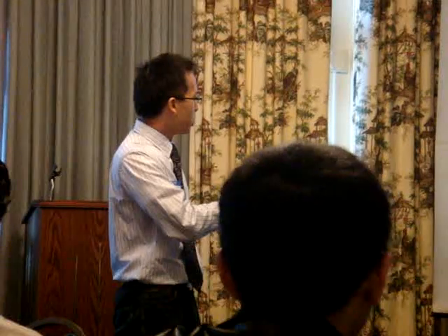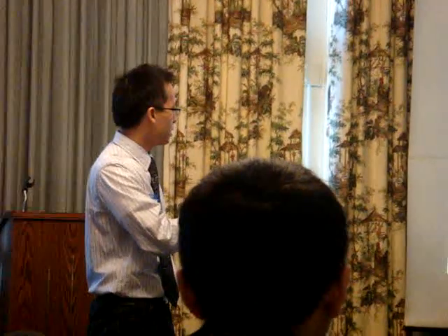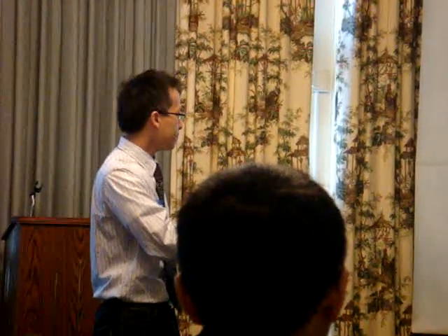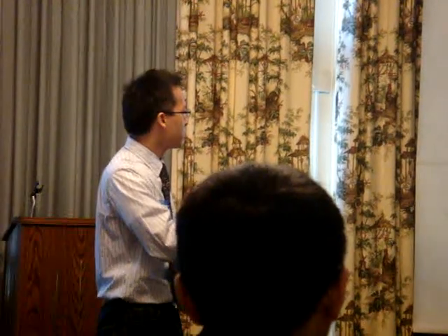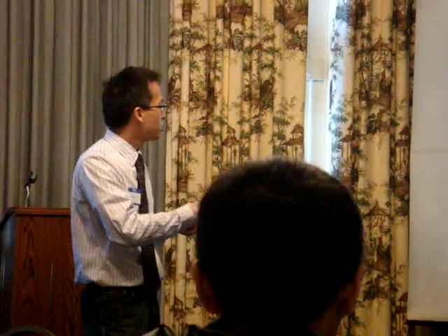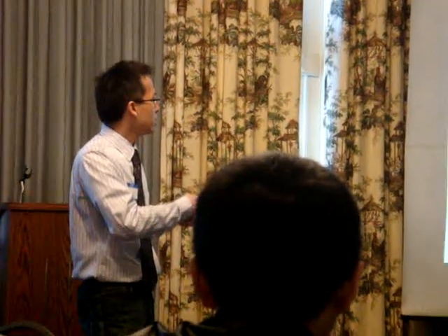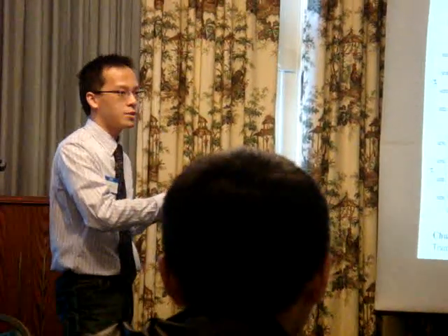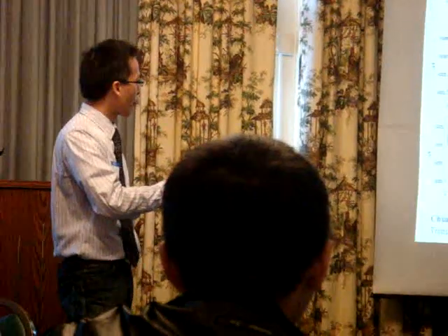When we excite the shell, most of the signal actually comes from the hole, and we found hole transfer through the interface is also very fast, roughly 500 femtoseconds. However, the relaxation rate compared with the electron is actually 100 times slower.